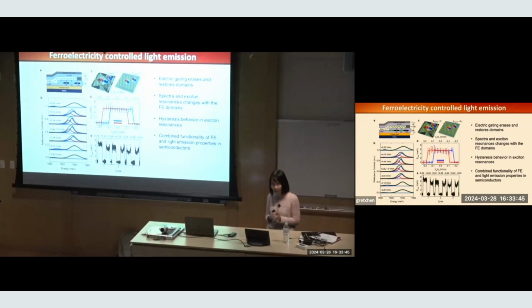the light emission properties. So I can actually apply a global gate. I can erase and restore the domain. I can do this over many cycles. And then as I add the electrical field, the spectrum changes. This is a raw spectrum, but if I follow the Stark-shifted peak, I have this funny-shaped hysteresis behavior. So this is multiple cycles of switching monitored by the exciton emission peak shift.